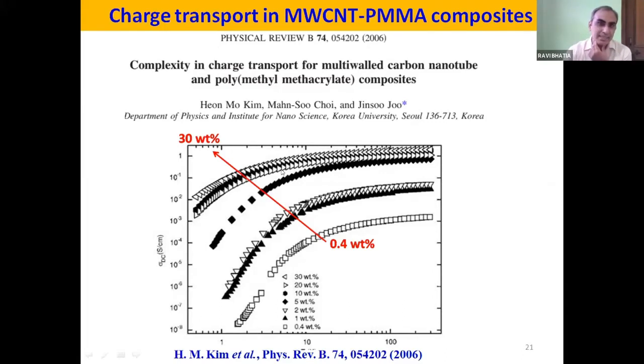I will just take another example: if you have a 30 weight% sample, that means you have added 30% of CNTs by weight into a composite. It should show metallic behavior. For example, I have presented another work in which aligned and randomized samples were taken, and we studied their charge transport, which comes out to be metallic, and magnetoconductance also corroborates it, showing that the results are authentic and there is no artifact in the result.